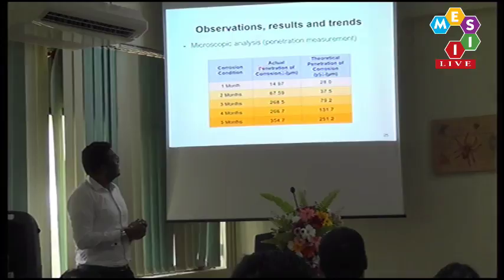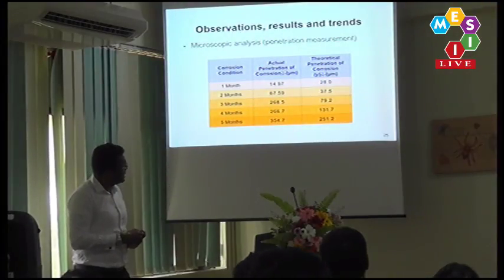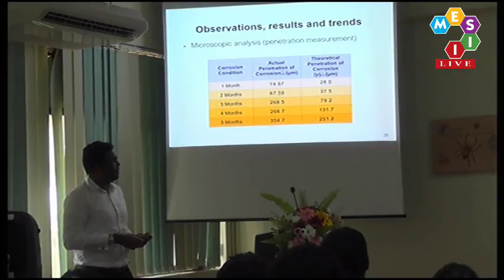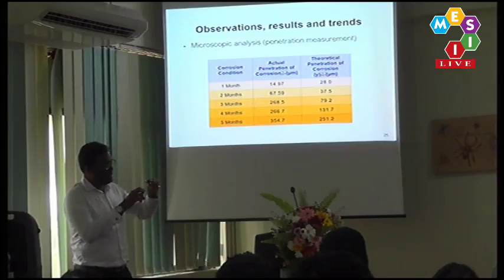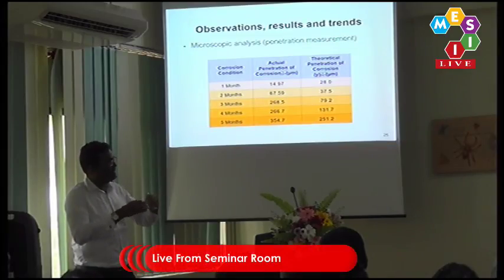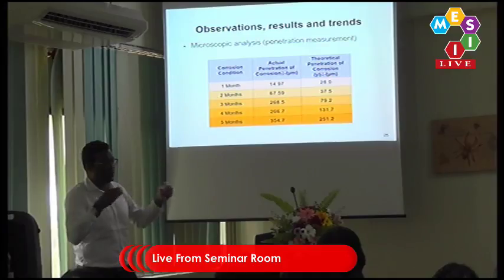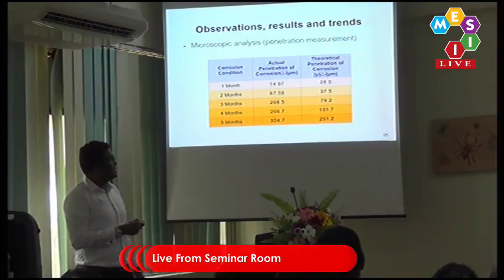And this is sort of the measurement of my microscopic analysis. These are the actual depths I got. The theoretical depths can be reverse calculated from the graphs shown earlier where there was a disparity. So the disparity is alluded to a certain depth that goes in from all four sides. This is pretty similar. We were amazed. This showed quite a correlation.